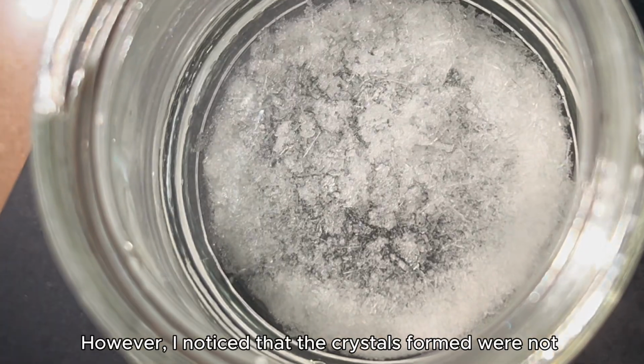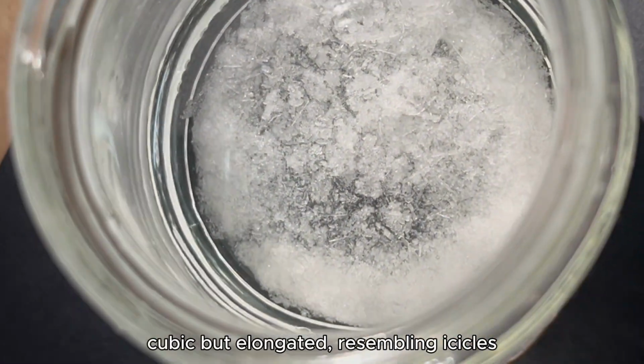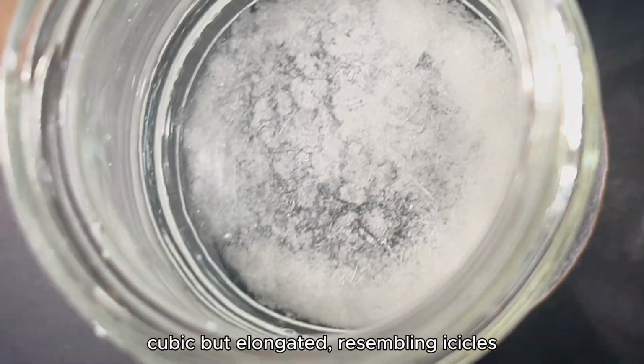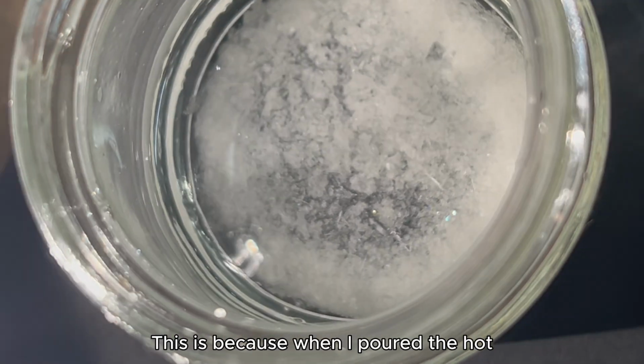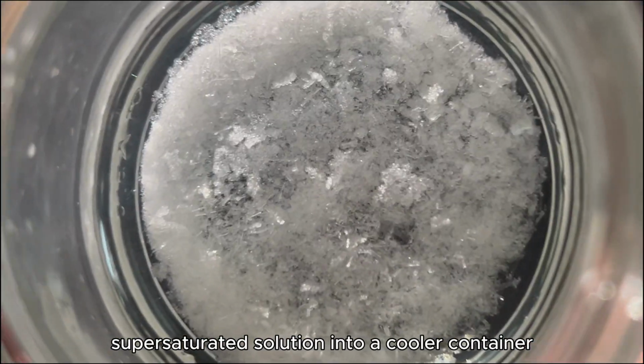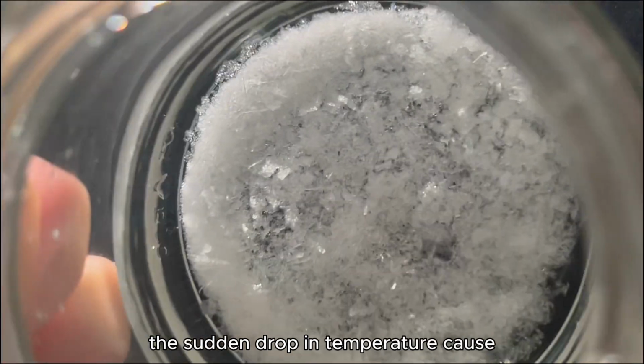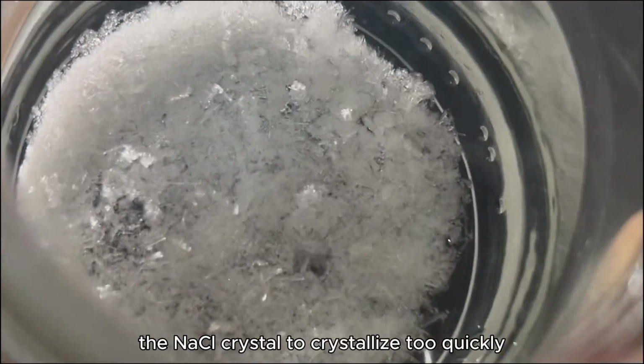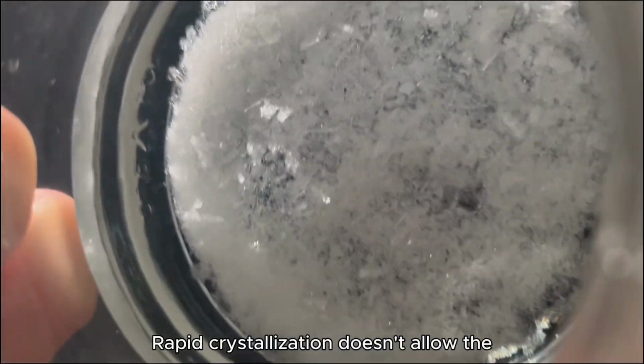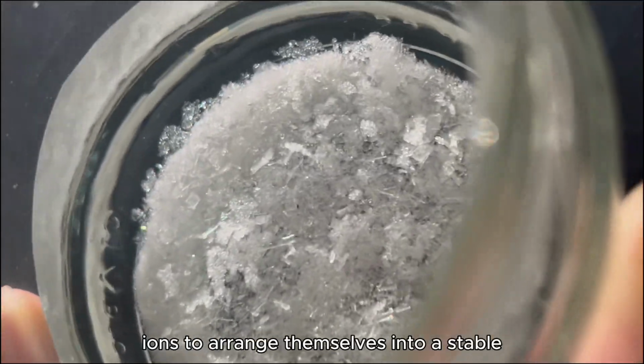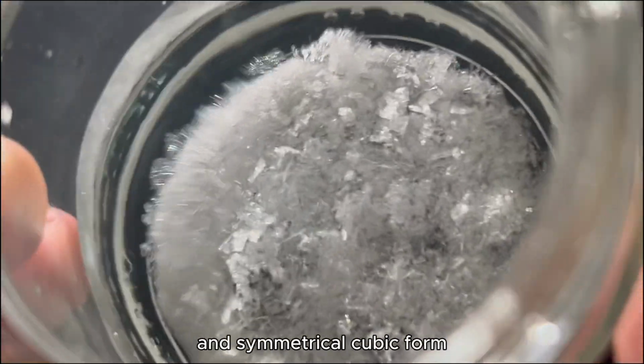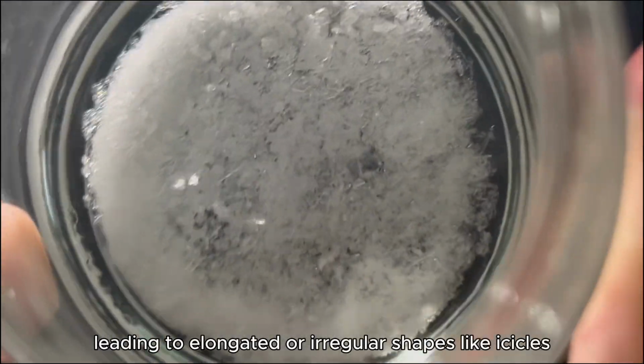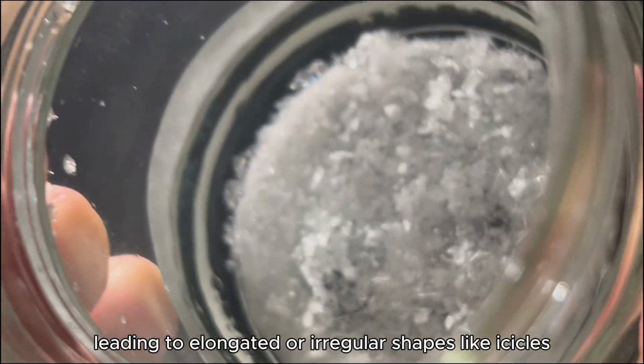However, I noticed that the crystals formed were not cubic but elongated, resembling icicles. This is because when I poured the hot supersaturated solution into a cooler container, the sudden drop in temperature caused the NaCl to crystallize too quickly. Rapid crystallization doesn't allow the ions to arrange themselves into a stable and symmetrical cubic form, leading to elongated or irregular shapes like icicles.